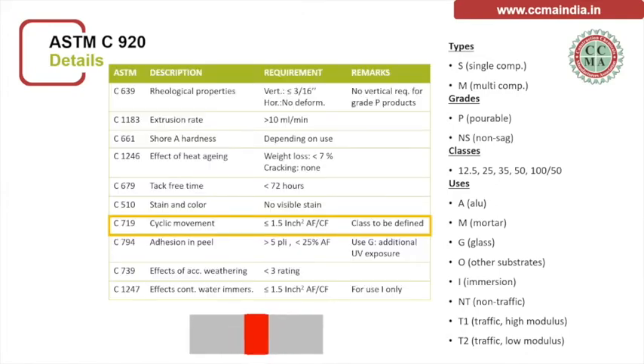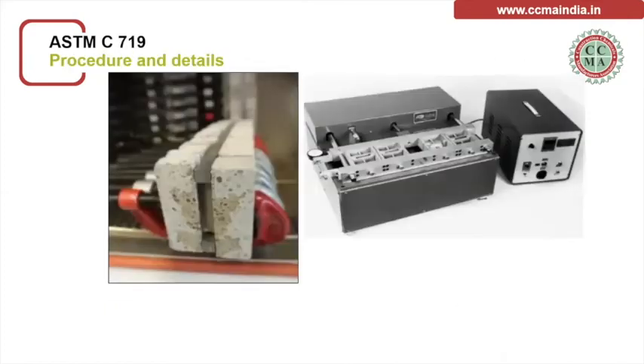One of the important test methods in ASTM C920 is C719. Now, this is an important test, and the specifier needs to appreciate that, in this rigorous testing, the sealant goes under cyclic movement to evaluate the performance of the sealant. Okay. So this is the apparatus for testing the sealant for cohesive and adhesion failure under cyclic movement according to the Hockman cycle. So you have a C clamp and the compression extension testing machine with a console unit.